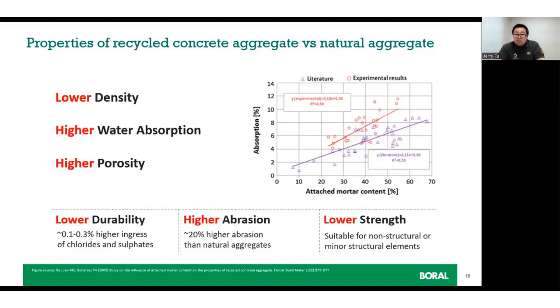Literature suggests that construction demolition waste aggregate contains about 0.1 to 0.3% higher chlorides and sulfates than natural aggregates, while the recycled aggregates have a higher abrasion. However, on average, they are still suitable for both concrete use and roads.